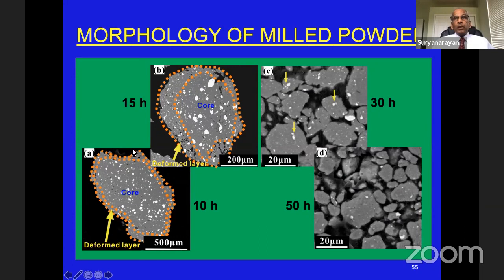So if you mill this powder, obviously there is going to be a deformation taking place on the surface of these metallic glassy powder particles. You can see these metallic glass powder particles, white particles here, and then the grayish area is aluminum 7075. This is 10 hours. You increase to 15 hours, the deformed region, the amount is increasing, and then you go to 30 hours, 50 hours, like that, you'll be able to see the more uniform distribution of these, and then this is not almost very clear at all.